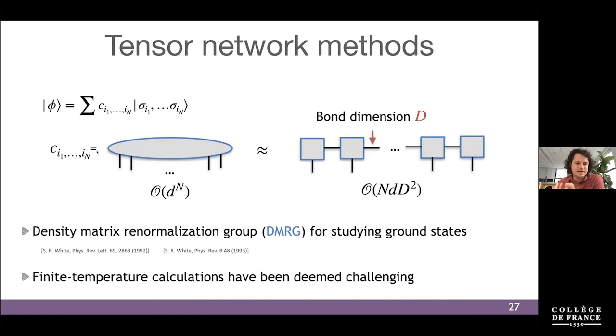So we represent a big tensor, which has d to the power of n coefficients, where d is the number of local degrees of freedom, which is 4 for the Hubbard model, and n is the number of sites. If you want to store all of these coefficients, this scales as d to the power of n, which is of course a very big number. But if we represent this as a matrix product state with a certain bond dimension D, the number of parameters scales linearly with the number of sites, times the local dimension, 4, times the bond dimension squared. And so this is, of course, very favorable. We go from an exponential scaling in the number of sites down to a linear scaling.